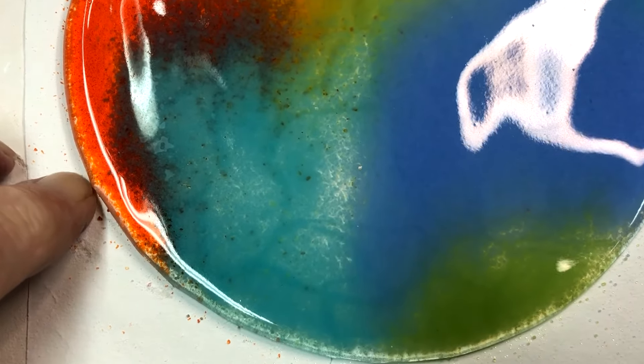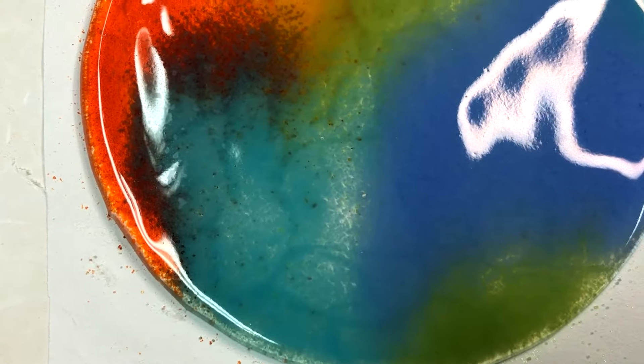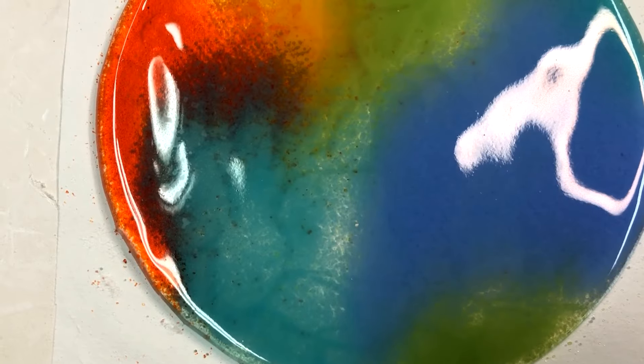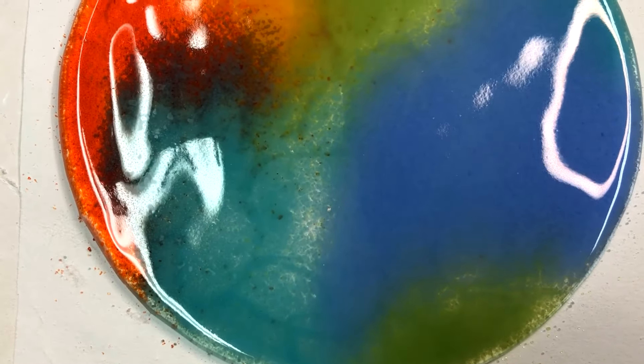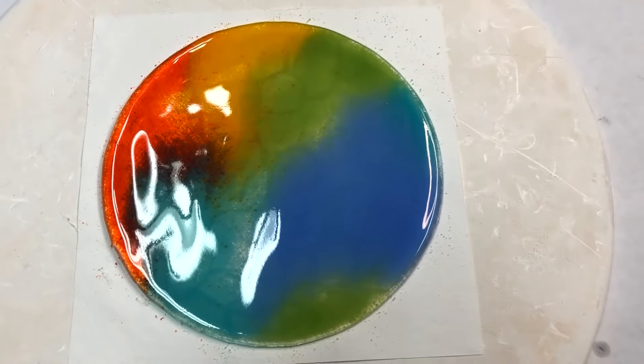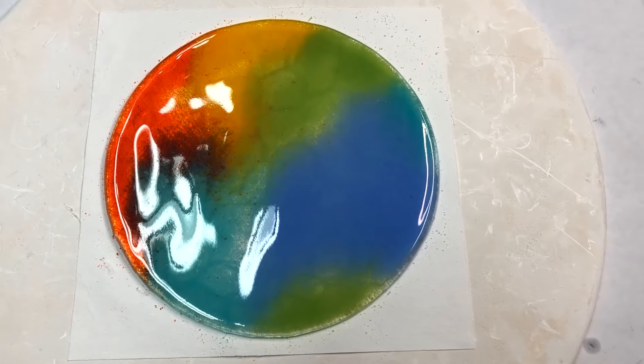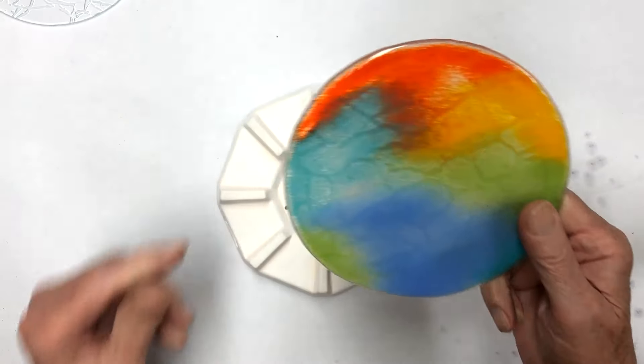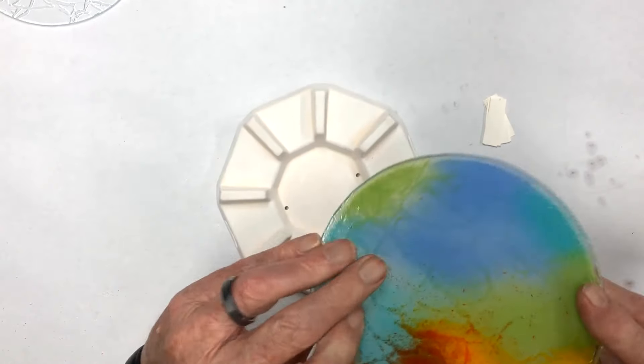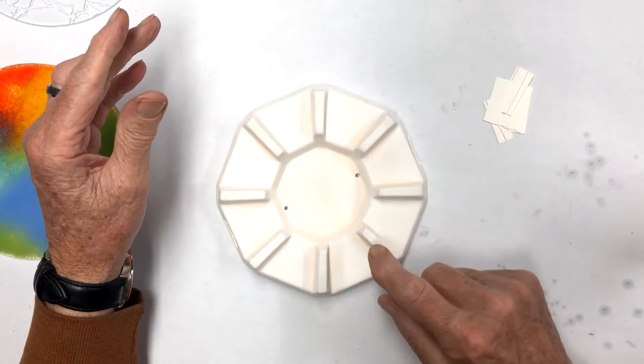There's a little bit of a piece of frit right here, so be careful — don't run your fingers along the edges because any frit hanging out is just as sharp as a knife and will cut you. I'll put this on the grinder and just hit it really lightly. Then we'll put it on the slumping mold and get ready to slump it. It shrunk an eighth of an inch, so that's why I wanted to make it bigger. This is six and a quarter across here, so I'll just have a little bit of an overhang on the mold.